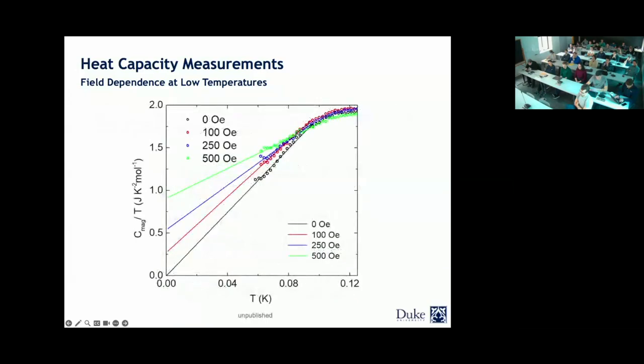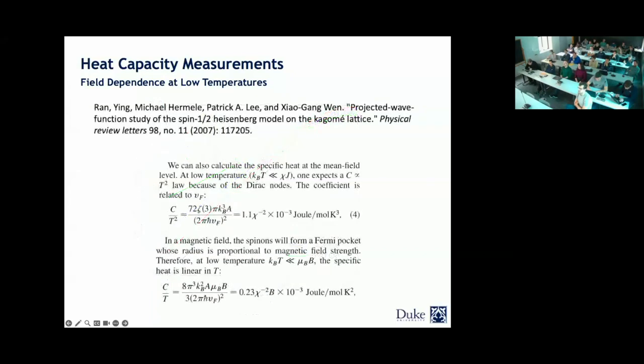That is what we did. We actually looked at the data down to 50 millikelvin. Here you're looking at the data at zero field, then 0.01 Tesla, which is 100 Oersted, and then 500. The reason for this is that we still need to be in this range, which itself needs to be within this range. So at very low temperatures, that would be comparable to that.